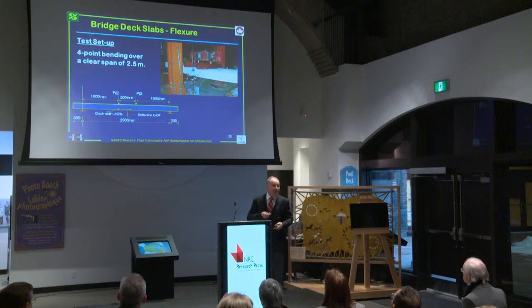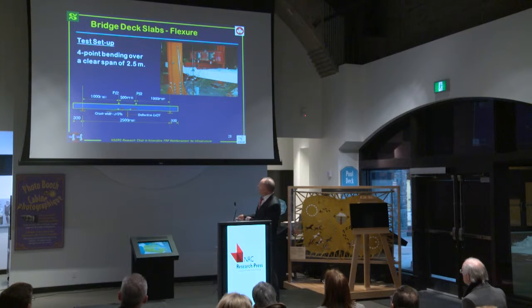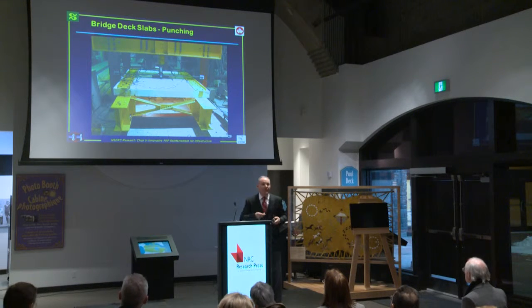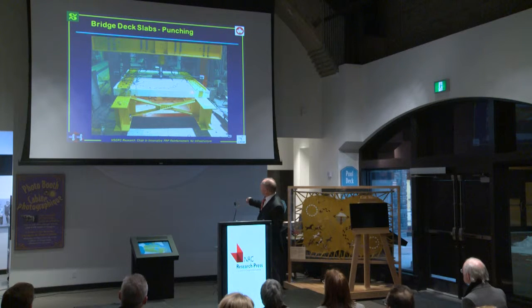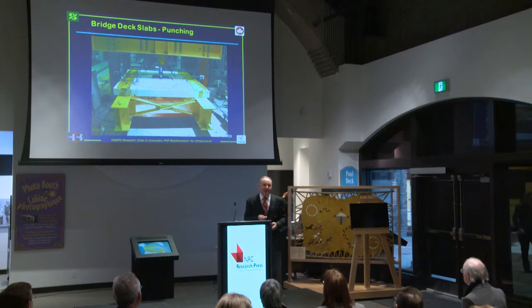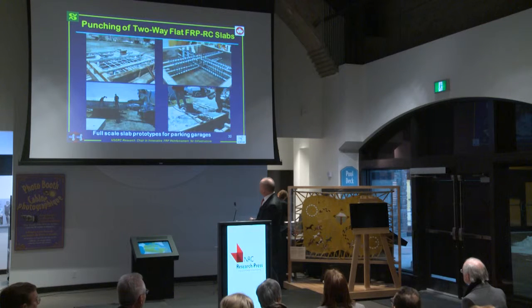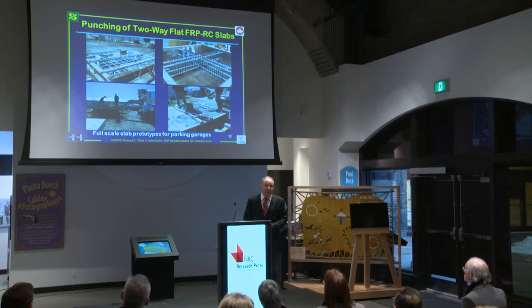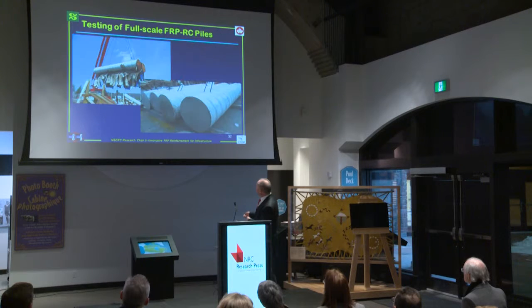We also did structural testing, using, as you can see here, slabs simulating bridge deck panels. This is the same as when you are moving with a truck over this slab of the bridge deck. You can see here the girders, and this load is simulating wheel load. We even go 3, 4, 5 times the design load permitted by the Canadian Bridge Design Code. This is really to look at how this material is behaving, what the performance of this material is, and its potential. We also did this for parking garages, with two-way slabs as you can see in parking garages, and we tested them under load.